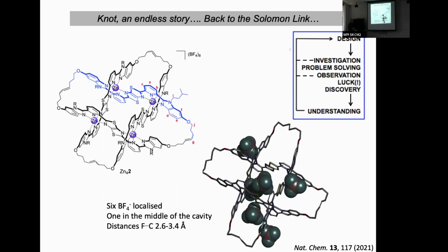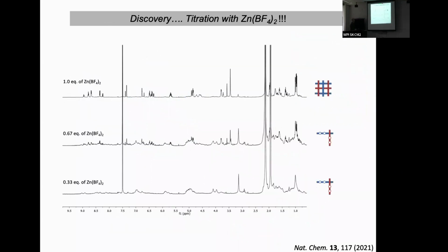That was of a BF4 salt. And he noticed that in the crystal structure, these BF4 anions were actually in the center of these cavities. So he switched from using zinc triflate to zinc BF4. And when we did that with exactly the same ligand, immediately we formed, very quantitatively, a very simple NMR spectrum. And this turns out to be the 3x3 interwoven grid.